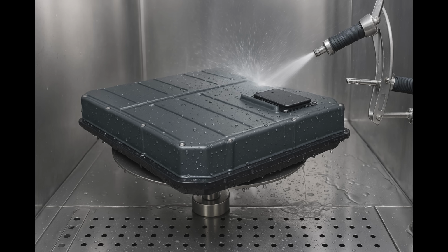Real-world risks of IP69K failures include water forced past gaskets at high velocity, especially at connector pins or vent ports, hot water degrading polymer seals or adhesives, jet erosion of pressure relief membranes, false BMS triggers due to shorted signal lines or sensor anomalies, and it could also lead to thermal runaway. It's one thing to keep water out of a static enclosure. It's another to do it while the vehicle is getting pressure washed daily or hit by road blasts at 70 miles per hour. Some of the design challenges include connector interfaces, which need dual lip or triple lip sealing designs. Vent membranes must balance pressure equalization with splash resistance and often employ some kind of a splash or spray guard to protect the membrane. Mounting fasteners must be designed to avoid capillary leakage paths, and thermal expansion of materials must not compromise long-term seal performance.